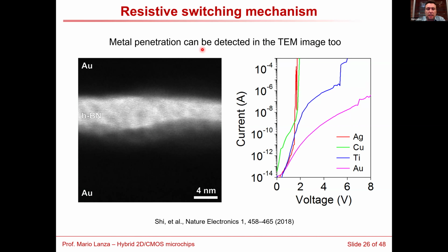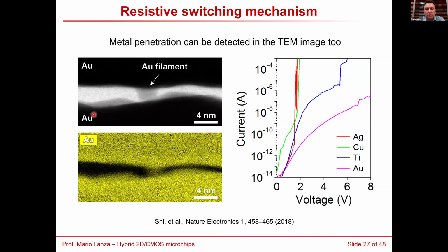Regarding the switching mechanism, we made cross-sectional TEM images in stressed devices, and we observe that the boron nitride layer looks contaminated by particles coming from the metallic electrodes. Actually, if we heavily stress the devices, we can clearly observe the formation of a gold filament inside the boron nitride.